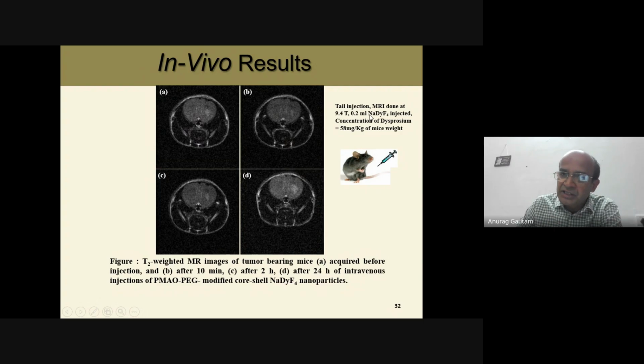If you are not using this sodium dysprosium fluoride (NaDyF4) and instead use gadolinium, that will give more whitening contrast compared to the tumor area. So we can use either model, dysprosium or gadolinium-based contrast. One time we see that compared to this, T2 will be darkened, and when we use T1, compared to this, the whitening will be further enhanced.